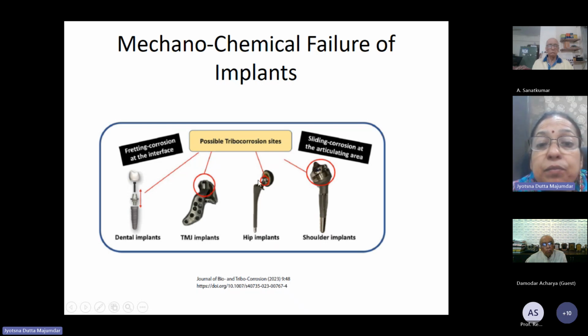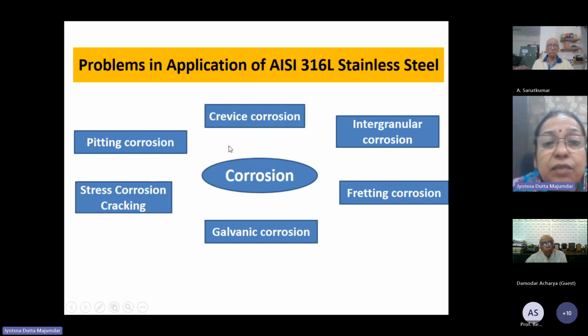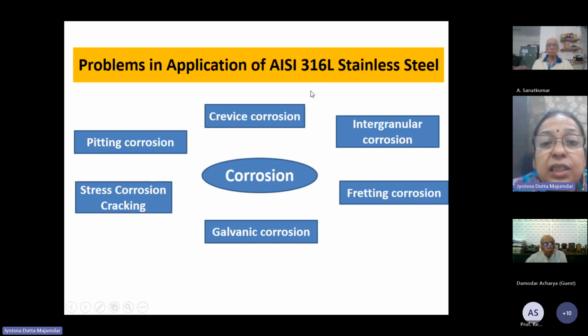And then TMJ implants, hip implants, again wherever there is an oscillating motion between two surfaces, and the other surface is solid, there is fretting corrosion, which causes a more accelerated rate of degradation of the metallic materials. So these are different types of corrosion usually encountered by AISI 316L stainless steel, specifically because titanium has a little higher corrosion resistance. Titanium does not undergo pitting corrosion, or intergranular corrosion to a large extent, but it undergoes typical biofouling corrosion, and also crevice corrosion and tribocorrosion.